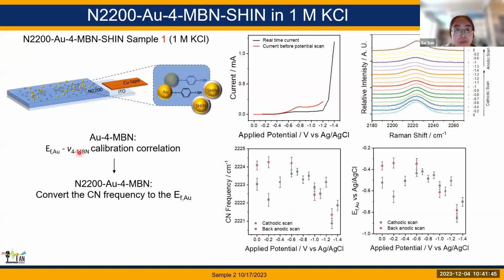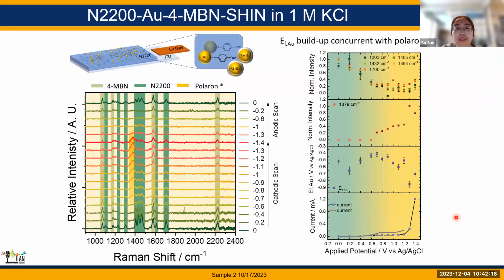So then we can use the previous calibration correlation between Fermi level of gold and CN frequency to convert the nitrile frequency directly to the gold Fermi level. And we can see that the Fermi level of gold first stabilized at around -0.4, and after the N2200 can be reduced, the gold Fermi level shifts from -0.4 to -0.8.